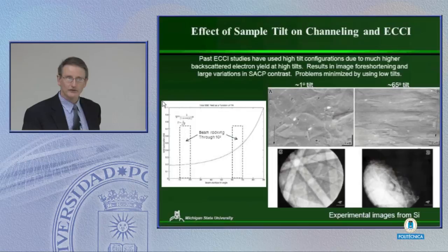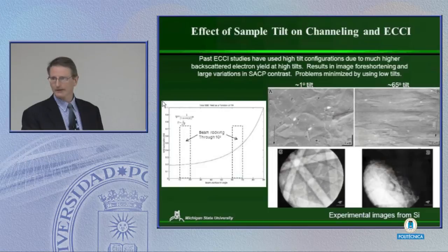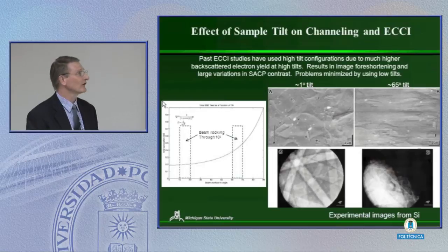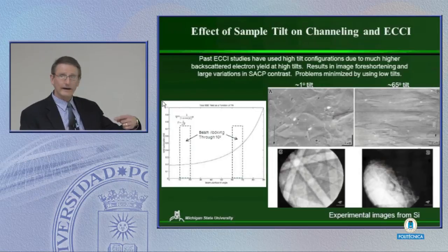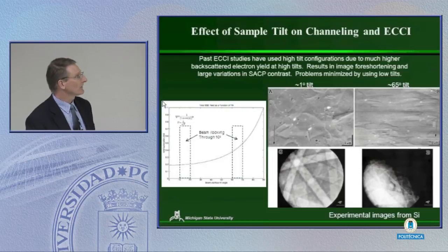But there's some disadvantages to that. First of all, if you're at high tilts, what tends to happen is your image gets squished together in one direction, and you have to focus differently as you raster across your sample. You can certainly do some corrections in a microscope to take care of some of those things, but it isn't necessarily an easy thing to do. This is the same area shown here, and this is a lot easier to understand what's going on here than it is here. But the thing that we have found more difficult is when we are collecting these selected area channeling patterns, if we do it at a high tilt, what happens is the intensity is varying as we're rocking the beam back and forth because that trajectory is changing.